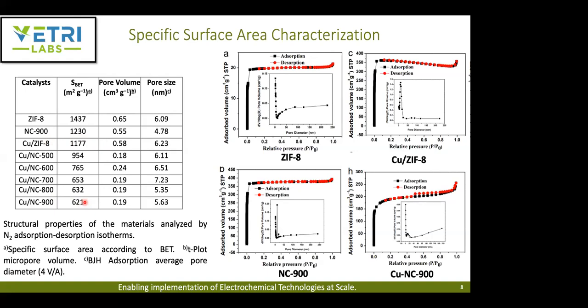And also the heavy metal zinc gets volatilized and evaporated, and the carbon gasification can also be attributed to the development of mesopores in the nitrogen doped carbon and copper nitrogen doped carbon. And also you destroy this cubic structure at a very high temperature, right? So that is what contributes to the presence of more macropores. As a result, you can see in this inset, comparing the ZIF-8 and the copper nitrogen doped carbon at 900 degrees Celsius, there is a decrease in micropores, and it's mostly mesopores and macropores. So for an ideal 3-dimensional porous structure as a good catalyst, you need a synergistic effect from all the different pore sizes. This could reduce the resistance to mass transfer and also expose more ORR active sites on your catalyst surface.